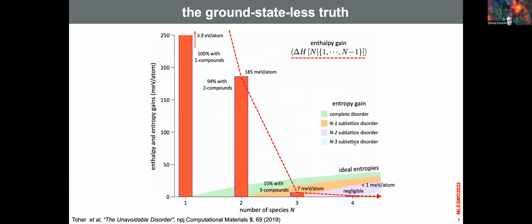And now about the numbers. Those are the numbers that we were able to extract, by Cormac, Corey, David, and myself. These are real numbers coming from our database. So if you add two compounds, meaning that if you mix A and B, you have an expectation of generating 185 milli-electron volt. If you compare this to room temperature entropy, which is roughly 25 milli-electron volt for two species systems, you see that 185 is much bigger than 25, so entropy does not play a role.